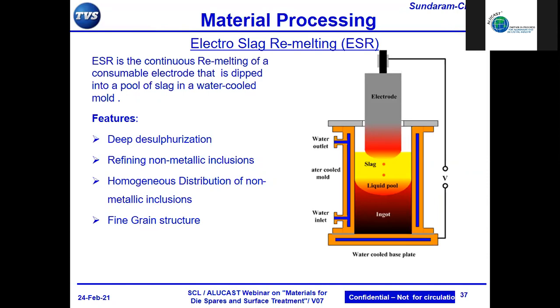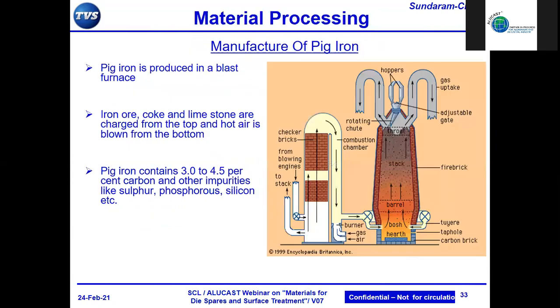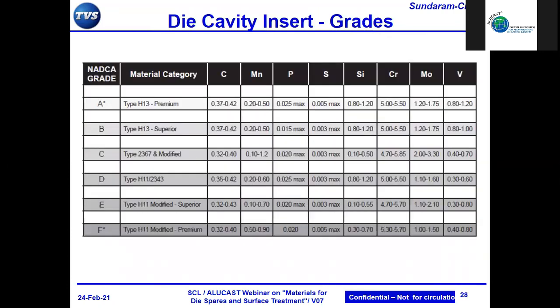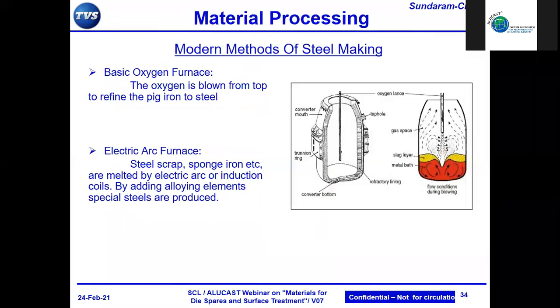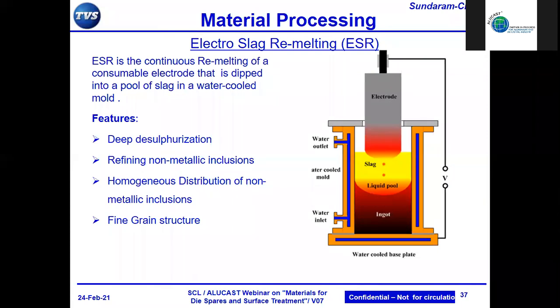In this, you have an electrode which is made out of the steel with the composition I showed earlier. The H13 premium, H13 superior, these are the chemical compositions that are made. And they go through this process called ESR. The electrode is made with that composition, and this slag is made in such a way that the inclusions in this electrode get dissolved in the slag. So drop by drop, the metal goes into the water cooled copper crucible and gets solidified and forms an ingot.